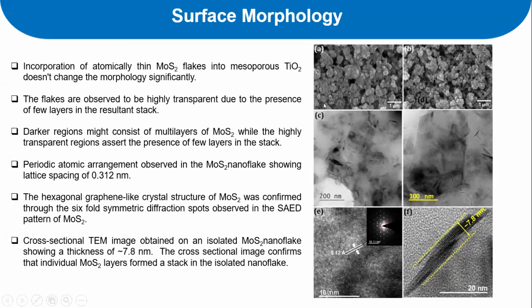So basically, titanium dioxide is a porous structure. It's a nanoporous structure, as we can clearly see from the scanning electron microscopic morphology study. So we have a lot of pores. Through these pores only, the organic dye molecules or quantum dots in the excitonic photovoltaic technology will enter and then be adsorbed on the surface. We have then introduced 2D layered moly sulfide into that. If you look at that, the pores are still existing after coating also.